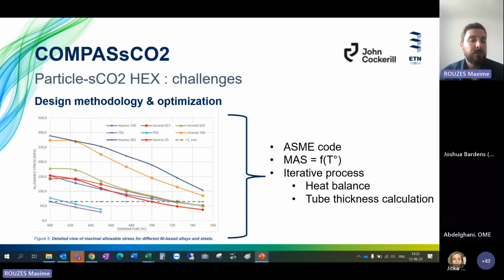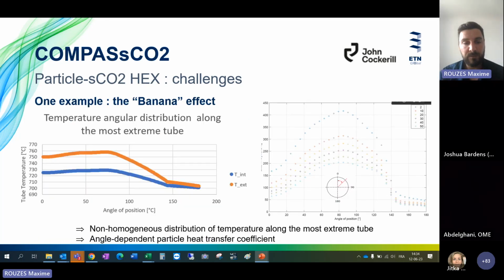Very quickly, at John Cockerill we are used to utilizing the ASME code for this case, so we based our analysis on that. We compared the different allowable stresses, especially at very high temperature, as you can see here, above 600 degrees C, which is almost 100 degrees more than for molten salt. And then it is also temperature dependent. So we did this process over several rounds, calculating all that. And then we ended up with a geometrical arrangement and also a diameter of the tube. And we did that for different materials and compared.